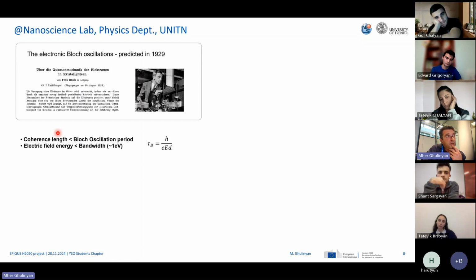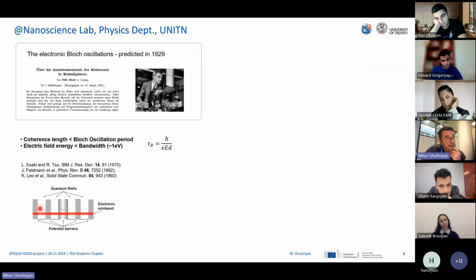So this idea remained a theory for many, many decades, and only with the advent of electronic superlattices by Esaki and Tsu at IBM research, when they first realized, I suppose with molecular beam epitaxy, coupled quantum well structures, which have a larger periodicity. And a large periodicity means you have shorter Bloch oscillation times. Only then, even after 20 years of that system's invention, did people observe electronic Bloch oscillations in electronic superlattice structures, in coupled quantum well structures. So eventually the ideas of Bloch were confirmed for electronic structures, and people were happy with that.